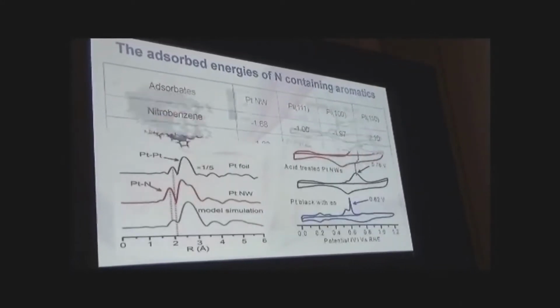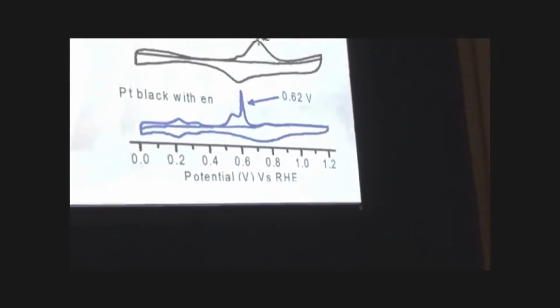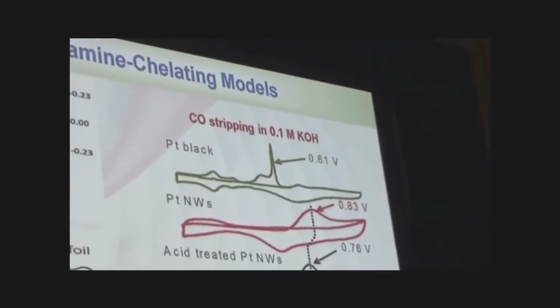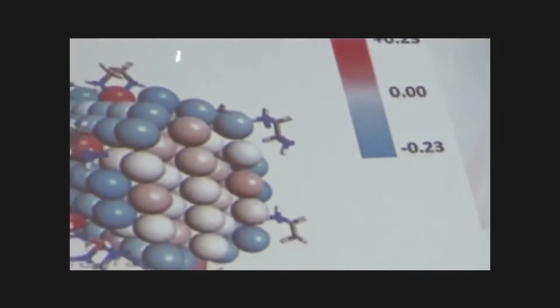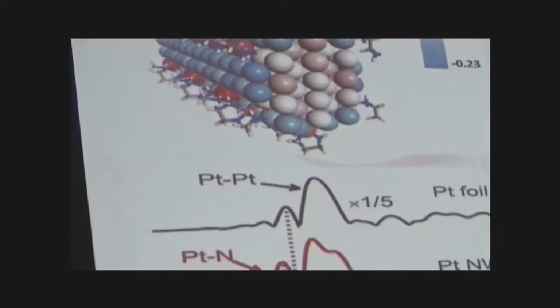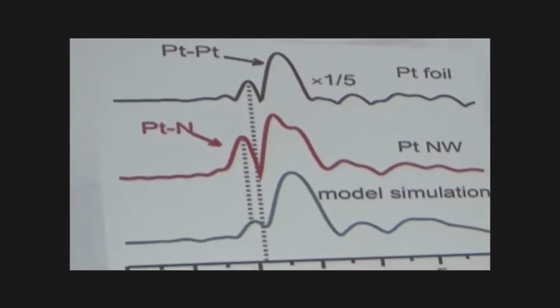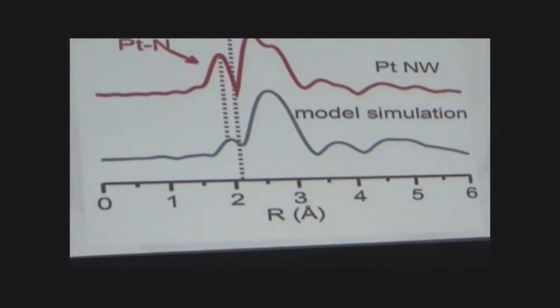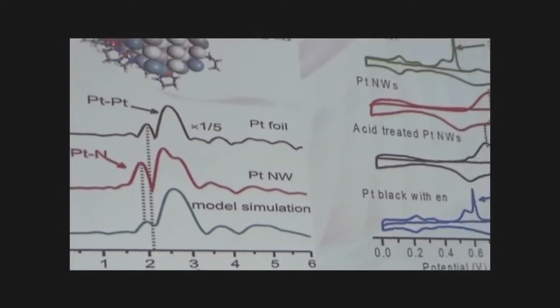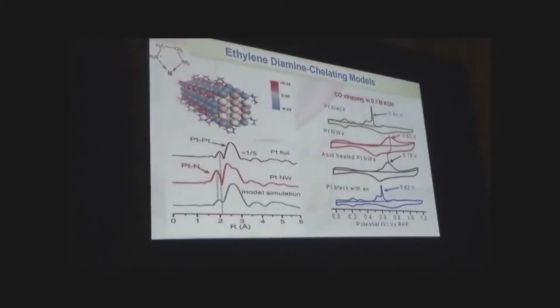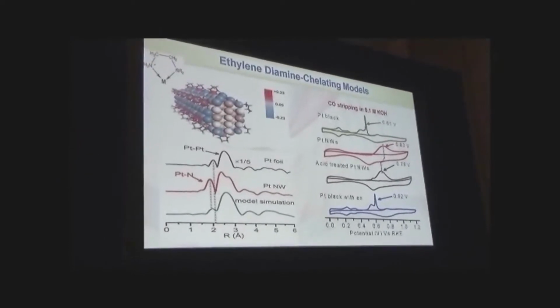Yes. Because during synthesis, we use oleylamine, and the oleylamine is strongly adsorbed on the ultrathin Pt nanowire. It still has oleylamine, and with oleylamine, the surface becomes negatively charged. So here the blue indicates the surface is negatively charged rather than zero.